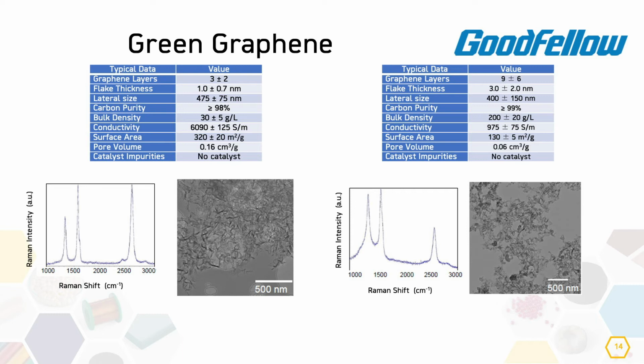One of the most important features of this graphene is that, as I said, it's slightly crumpled. They do not stack together, all right? While if we produce graphene by an exfoliation process, for sure they are stacked. So this feature is ensuring optimal electrical, thermal, and mechanical performance. We have estimated the electrical conductivity, which is very important for graphene, and we already know that graphene is a highly electrically conductive material, the thinnest material in the world, the lightest material in the world, and the best material in mechanical strength as well. So we have estimated the conductivity by 4-point probe measurements of compressed pellets, and also the surface area of graphene, which is very important as well, by the BET method.